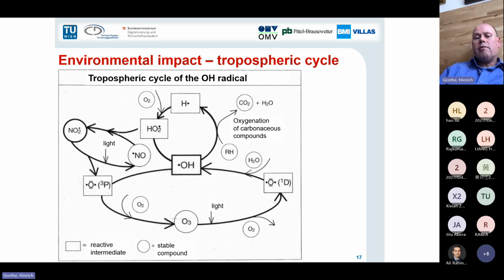And this is very reactive chemistry. And these HO2 radicals then react with the NO and very quickly oxidize the NO back into NO2, and then you can start the whole cycle again. So a very crucial process in all this is, of course, the formation of the OH radicals.